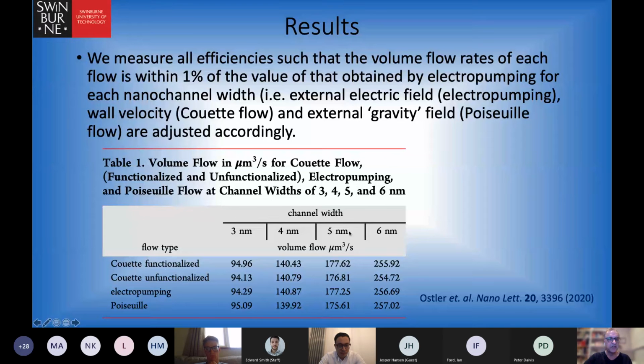So quickly, some results. The way that we do it is that we do a simulation for electropumping. We choose a particular electric field intensity and frequency. We look at nanochannels of different widths. We look at the flow rate within the electropumping simulation. And then we do simulations for Couette flow, for functionalized Couette flow, and for Poiseuille flow, such that the flow rates are within 1% of what we got for electropumping. So we adjust the other parameters accordingly, and that way we can be sure that we're comparing apples with apples, so to speak. We're comparing systems that have the same flow rates within 1% error.